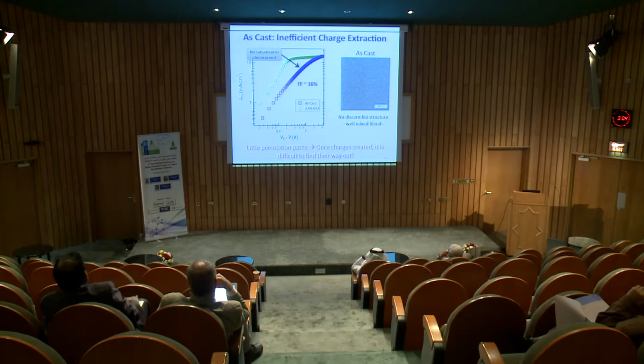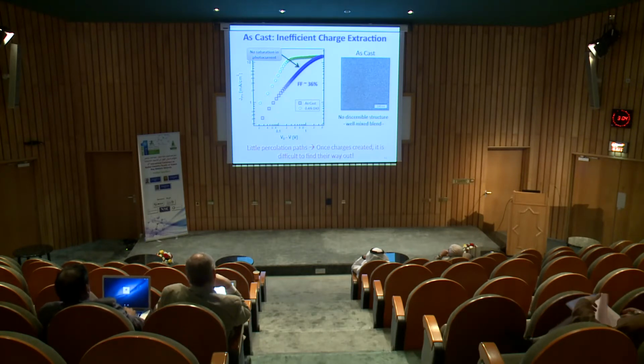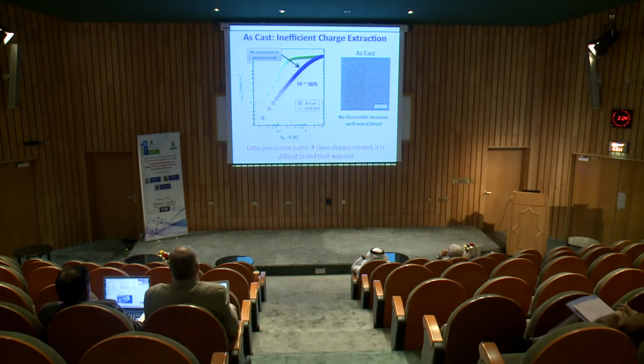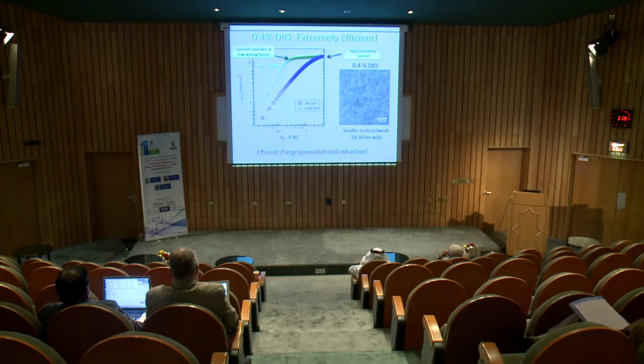So you have the two donor and acceptor blend quite well. When they blend quite well, they also have little percolation pathway. So after you generate the carrier, it's difficult for the charge carrier to find a way out of the device. And the stronger the applied bias you have, the more current you collect. So basically, the morphology can really impact many things, not just the charge generation, but also the charge recombination and transport, and therefore the device performance.